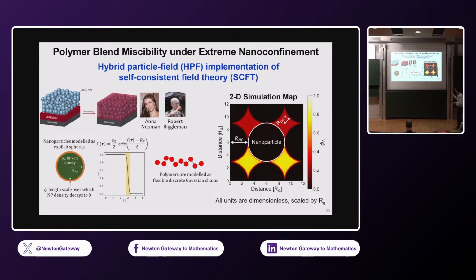Here we take basically self-consistent field theory, and my colleague Rob Riggleman has been really developing this method to look at these heterogeneous systems that have particles and polymers, okay? So to model the particle, we basically say there's a solid core, and the interface actually has this decay in its profile. And this is the simulation box. So we have particles that are packed in a square array, and we basically put two polymers in there and see how they behave.